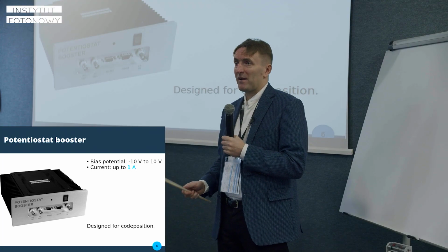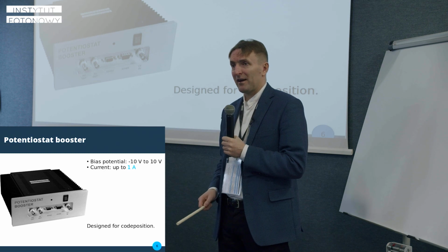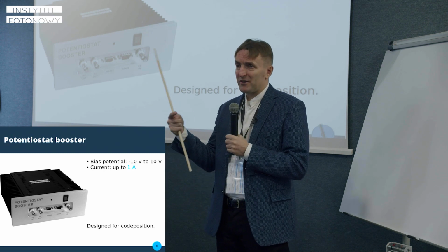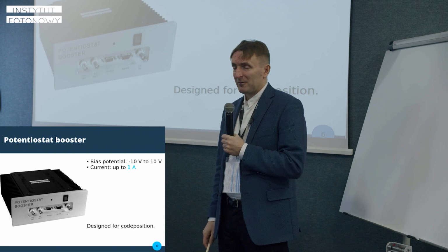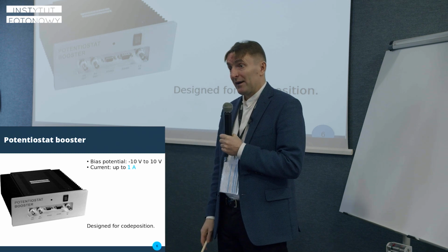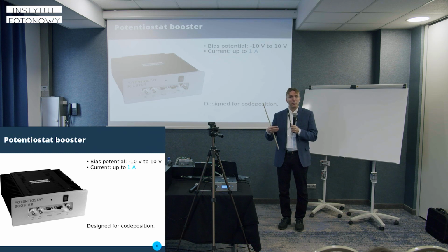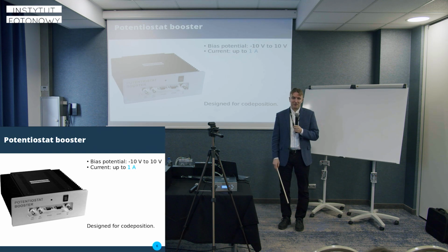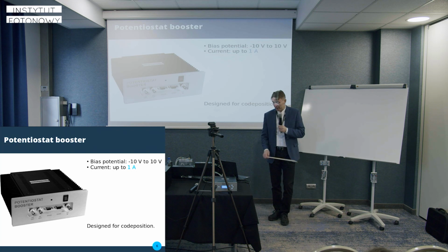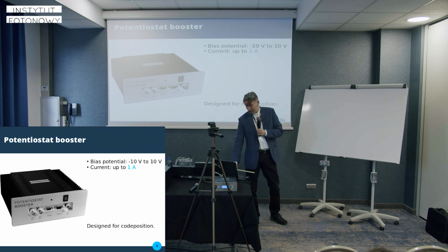So instead of using palladium and deuterium and trying to pack as much deuterium into the palladium crystalline network, he just co-deposited both at the same time, so he can control the load, or the stoichiometry, of the two components, and because of that he got reproducible results. So the booster here is designed for co-deposition. If you are interested in that, we have it.